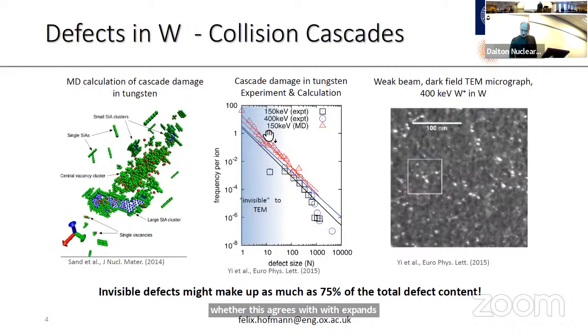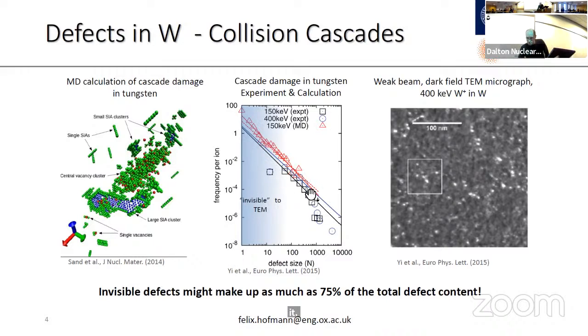So Shao Yi, a few years ago now, just before 2013 to 2015, did some beautiful TEM experiments where she looked at in-situ irradiation and then the accumulation of defects. And what she's plotted here are the TEM results, and superimposed on this is a triangle of predictions of the size distribution of defects that you would have from MD.